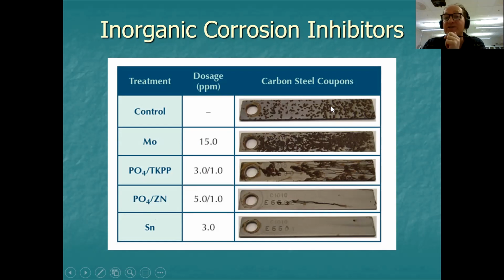And these are carbon steel coupons, which have been coated with the corrosion inhibitors and then exposed to a corrosion environment. And this shows you the dosage in parts per million of how much you've actually used. If it's in parts per million, that means it's not a very large amount. It's quite a small amount in reality. So here's the control sample with no corrosion inhibitor. And here we put in molybdenum of 15 parts per million, and it doesn't seem to have done very much. You could almost argue it's done nothing at all.